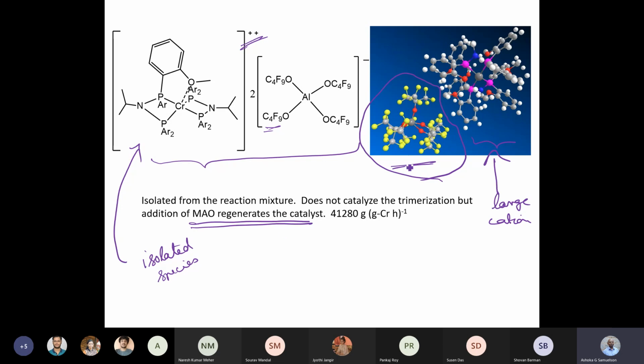So the reason why I'm saying that is that even if you have this large anion which is not really interacting with the chromium, that seems to deactivate the catalyst. If I add MAO, then I seem to be regenerating it. It's also possible that MAO merely generates a chromium methyl compound which can initiate the catalysis and promote it, and in this form the chromium is kind of deactivated by the presence of this ether. Although I don't understand how the simple addition of MAO, other than the fact that MAO has got Me minus equivalents. It's a hidden methyl anion, a masked R minus species. And this masked R minus is capable of displacing this ether group which is protecting the chromium from carrying out the reaction.